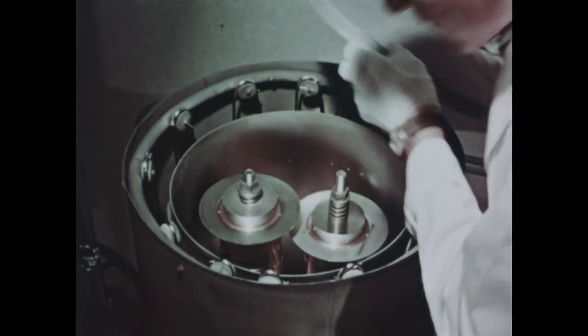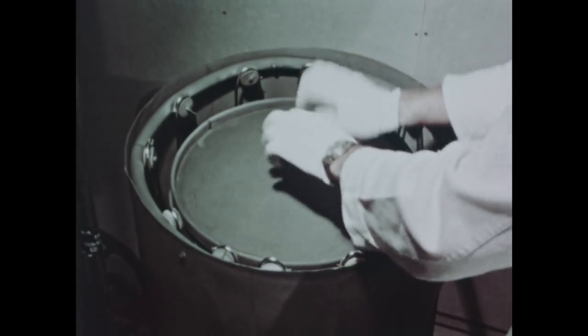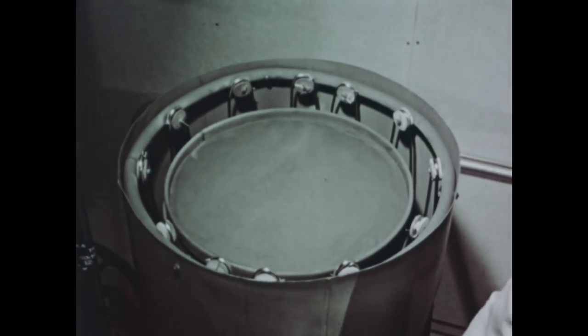The lid of the inner retort is put into place as well as the lid of the outer retort. This is a hydrogen atmosphere furnace, much like the one seen before. The parts are viewed through a window. The temperature is raised to about 1,010 degrees centigrade, at which the alloy shim 1,000th of an inch thick begins to melt. The alloy flag on the right of the back coupler is melting, an indication that the brazing has started. The temperature will be raised to 1,030 degrees centigrade for complete brazing.